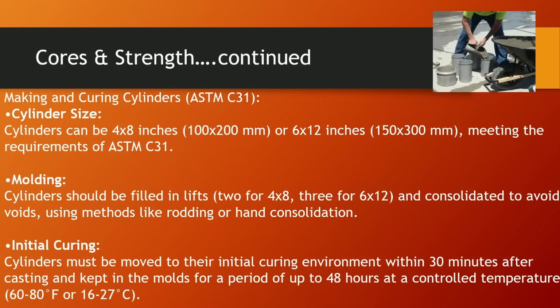Okay, making and curing cylinders. The cylinder size can be 4x8 or 6x12, meeting the requirements of ASTM C31. Molding, there is a certain way to mold the cylinders. Big surprise. By now, after watching all the rodding, all the tamping, and all the videos, you didn't think they were going to have instructions for molding. But cylinders need to be filled in 2 lifts for the 4x8, 3 for the 6x12, and consolidated to avoid voids using a method like rodding or hand consolidation.